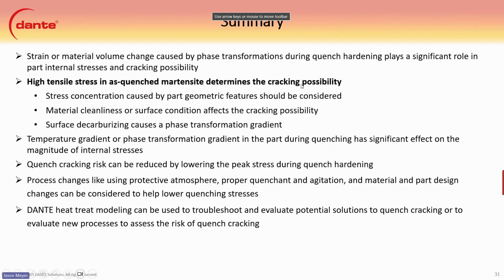All right, so summary. The strain and material volume change caused by phase transformations during quench hardening plays a significant role in the internal stresses and cracking possibility. Highest tensile stresses in as-quenched martensite determines the cracking possibility. It's really the big takeaway of today. Stress concentrations caused by part geometric features should be considered. So when you have the strains in the part, basically thin and thick sections, you will have a lot of stress concentrators in sharp geometric features.